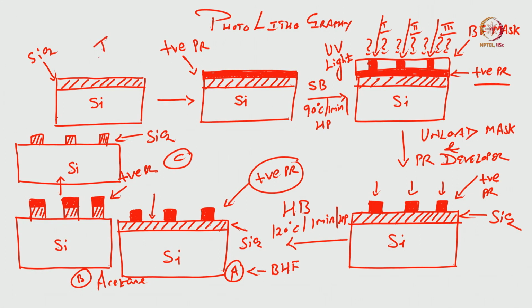So, in step 1 where we started, you can see silicon dioxide is on the entire silicon substrate. When we did this photolithography, we ended up patterning silicon dioxide in this particular fashion. We end up patterning silicon dioxide, as you can see on this slide. This is the beauty of lithography. The point is, by patterning the photoresist, if there is a material below it, the area covered by the photoresist will be protected, and the area not covered by the photoresist gets exposed to the etchant and will get etched, and you can finally pattern different kinds of materials.